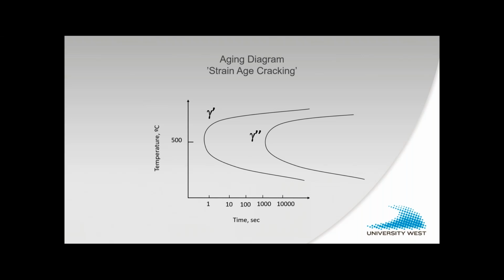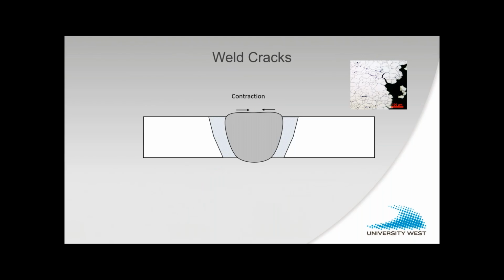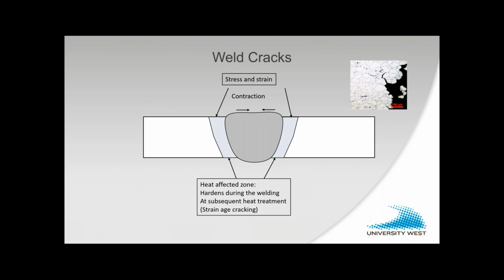So as I said, alloy 718 is primarily a gamma double prime hardening alloy, whereas Waspaloy and Haynes 282, for instance, are gamma prime hardening alloys. And one of the problems is that when you do post-weld heat treatment, you enter the precipitation nose of the gamma prime hardening alloys. So basically, as you weld something, you get contraction in the fusion zone, and this contraction in turn produces stresses and strains in the heat affected zone. And during the post-weld heat treatment, you get hardening, and as a consequence of this, you might get cracking. And this type of cracking usually takes place intergranularly.